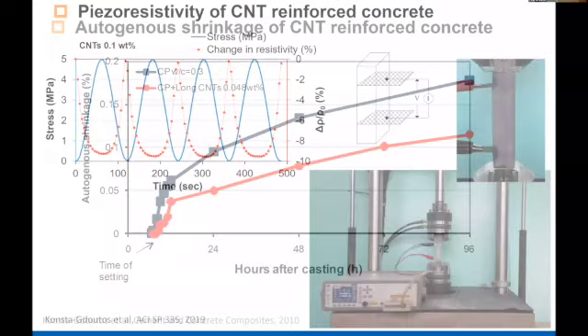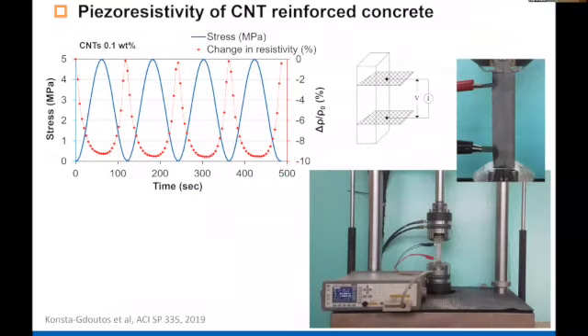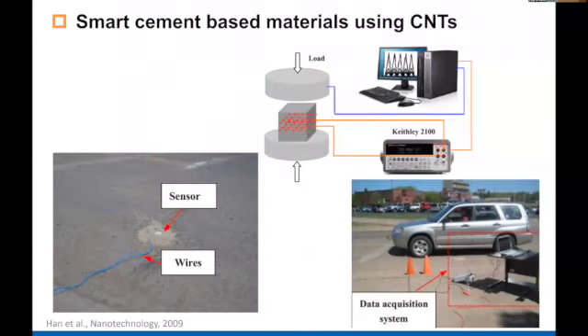Other people, as well as our work, found that this material, when cement is reinforced with CNT, could be used as a sensor. And they have excellent piezoresistive property. Here, for example, you can see the cyclic stress strain curve and measured resistance. And so we can see that you can use them as a sensor because they're linearly reversible, and you can measure remotely what the resistance is, and then you can also see what the internal stresses are. And for example, you can use them as a sensor, for example, in a highway.